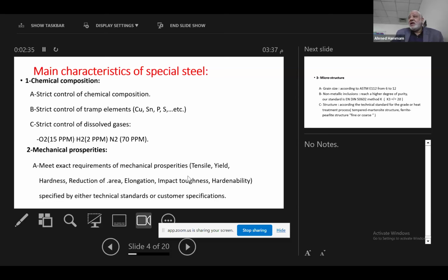This could affect the final application and give bad results for reproduction again. The main point for the special steel is controlling the dissolved gases, which are mainly oxygen, nitrogen, and hydrogen. If you take the normal values according to the standard, oxygen is around 15 ppm, nitrogen around 70 ppm, and hydrogen approximately 2 ppm. But for getting very good results after heat treatment, we have to make the levels of such gases more strict, especially nitrogen. We are trying to keep this at a maximum of 50 instead of 70. And for hydrogen, we are targeting 1 ppm.